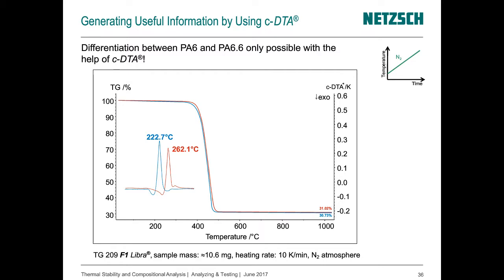Now we can say that the blue one is PA6 and the red one is PA66, because these temperatures, what we see here, are the typical melting temperatures of these materials, or lying in the typical melting range of these materials.